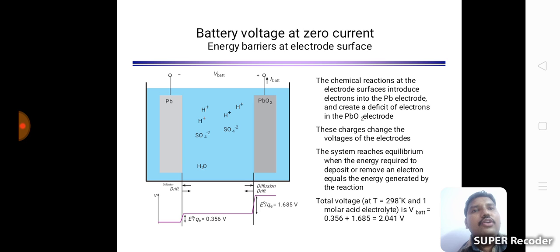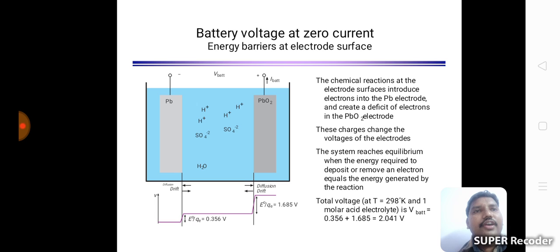Battery voltage at zero current: energy barriers at the electrode surface. The chemical reactions at the electrode surfaces introduce electrons into the lead electrode and create a deficit of electrons in the lead oxide electrode. These charges change the voltage of the electrode. The system reaches equilibrium when the energy required to deposit or remove an electron equals the energy generated by the reaction. The voltage at 298 Kelvin with 1 molar acid is 0.356 plus 1.685 equals 2.041 volts.